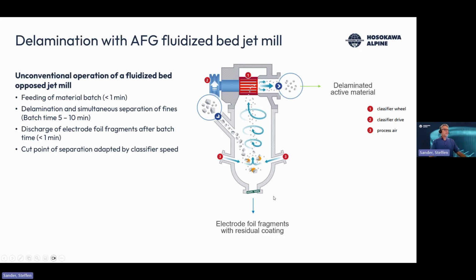So such a batch takes about 5 to 10 minutes, and the feeding and also the discharge is done in below 1 minute. So you can adapt the cut point by the classifier wheel rotational speed, and that's why you can very well fine-tune this delamination process here. We've seen that the pretreatment with liquid nitrogen, so like shock freezing of the material, can improve the delamination, but it's not necessarily economical.